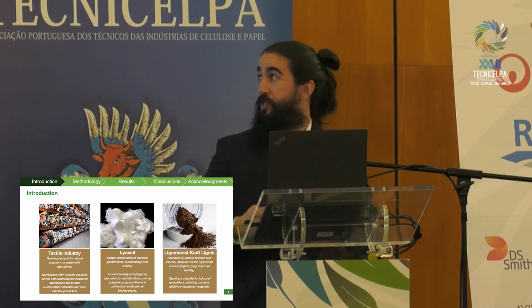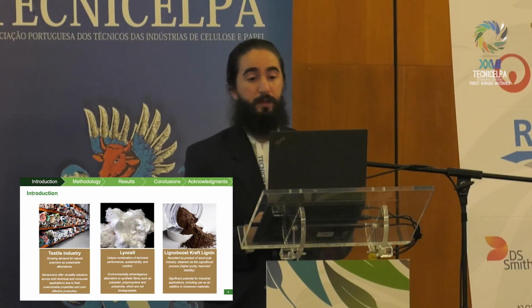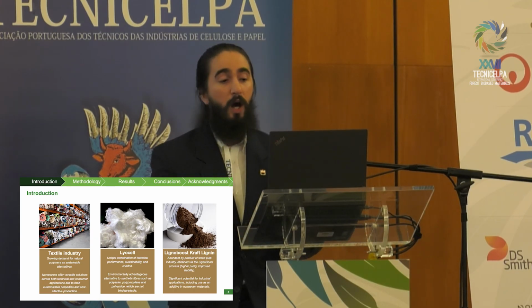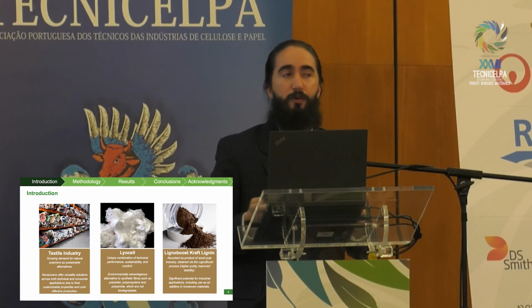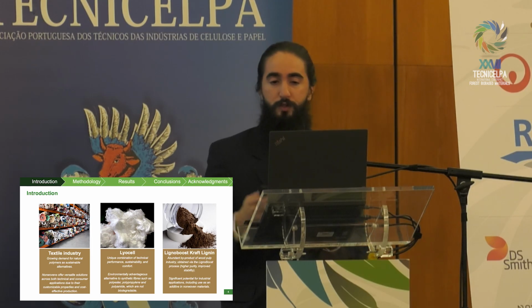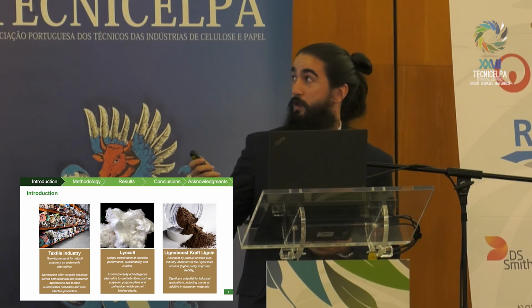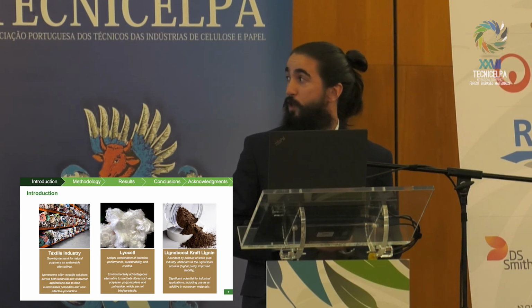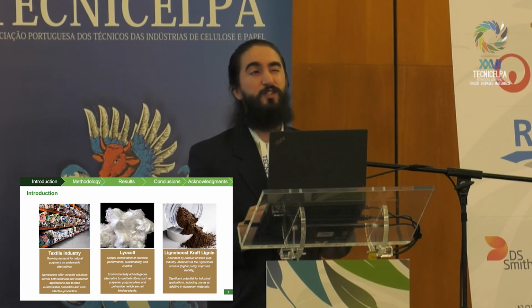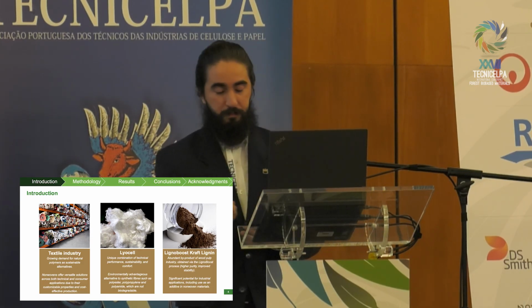And then our third component, our additive, in this case, we use kraft lignin provided by Altri Group, which is a byproduct of the wood pulp industry that is often underutilized. It's mostly burned for energy recovery. So we want to use this, which was purified via the LignoBoost process, to see if we could impart some interesting properties in our nonwovens.